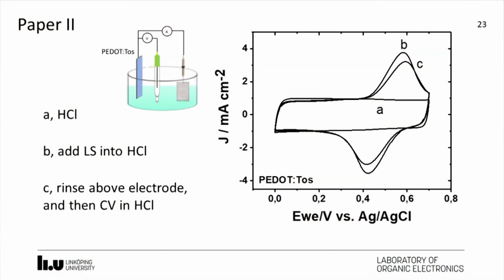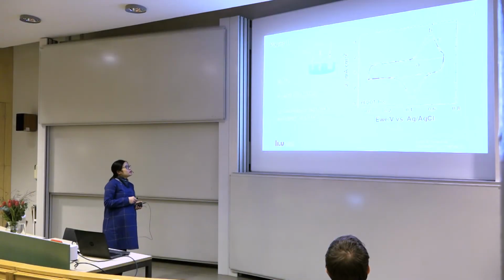So first, a film electrode was used in this experiment. In pure electrolyte, PEDOT:TOS is characterized by a typical capacitive current in the voltammogram. And when lignin sulfonate was added to the electrolyte, we observed an oxidation peak and a reduction peak due to the reactions of the quinones in the lignin sulfonate. What's interesting is that when we take the electrode out, rinse it carefully, and use it in a pure electrolyte without lignin sulfonate, the peaks were still there. So it means that lignin sulfonate was somehow adsorbed or bound onto the polymer.